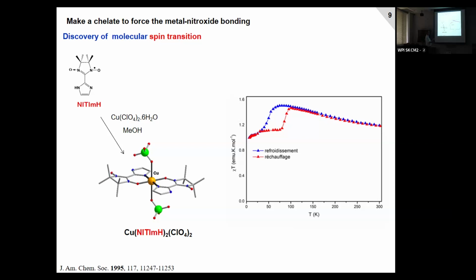So here you have a system with copper and the radical. The copper is 1 spin-half, the nitroxide is 1 spin-half, 2. For 1 spin-half, the value of chi-T is 0.4. So here you see that we have 1.2 because we have 1, 2, 3. 3 times 0.4 is 1.2. This means that we have almost the value for an uncoupled magnetic system. Then chi-T increases because you have small ferromagnetic interaction.